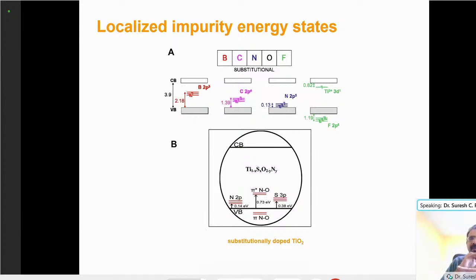This can form an additional level in between the valence band and the conduction band. N 2p, for example, will form an additional energy level 0.14 electron volt above the valence band. So you are creating a number of additional steps, so it's easy for the electrons to jump from one step to another step to the conduction band. You are making the job of the electron easier. So this semiconductor can be activated using visible light. You don't need ultraviolet light for the activation, and that has a huge commercial potential.